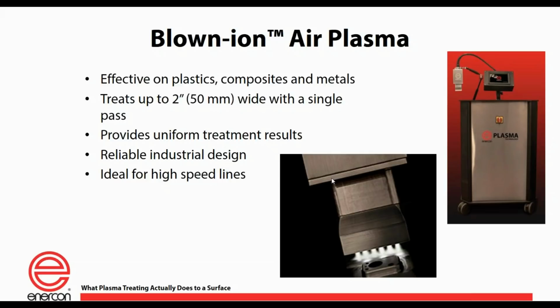Now, the blown ion 500 multiport, which is what you see here, treats up to 2-inch at the same intensity as the blown ion 125 that we just saw. This gives us the ability to treat much wider areas, much faster, and in much faster line speeds. The other alternative, generally, when you're talking about plasma, is some sort of method of moving or rotating the head around an axis so that you can get wider treatment areas. This may be very good for some thin films and things that are thermally damaged. But if you're trying to treat metals or you're trying to treat some larger plastic parts, you're not going to get the same level of activation. The ion density is how we refer to it, and that's just the amount of ions hitting one area at one time, and it is much greater with the blown ion 500 than it would be with any sort of rotary system.